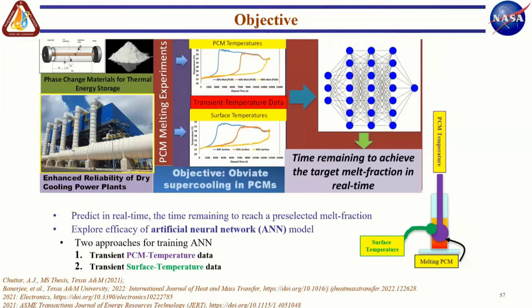Either they were the 3 thermocouples placed within the PCM at different heights, corresponding to different melt fractions, let's say 30, 60, and 80% melt fraction. We also looked at a configuration where we had 3 thermocouples mounted on the surface of the container containing the PCM. And instead of measuring the PCM temperature, it was just measuring the surface temperature.